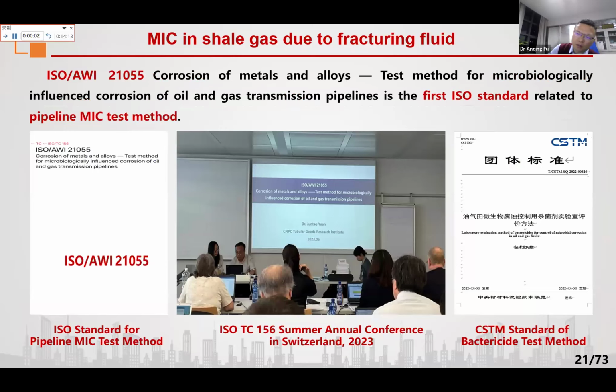Based on almost 5 years of research, our team proposed an ISO standard, the test method for the MIC of oil and gas transmission pipelines. This is the first ISO standard related to the pipeline MIC test method. Besides this ISO standard, we also developed several MIC related standards, for example, the test method as well as the anti-MIC materials.